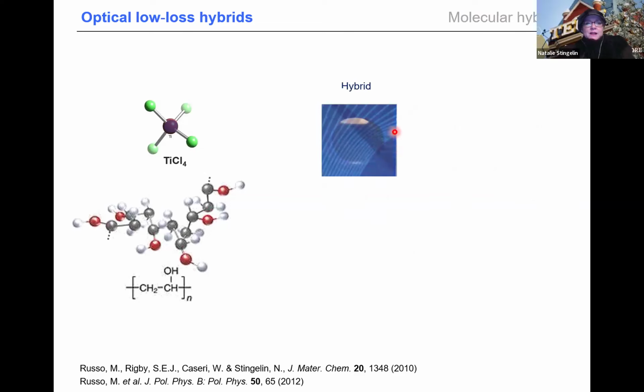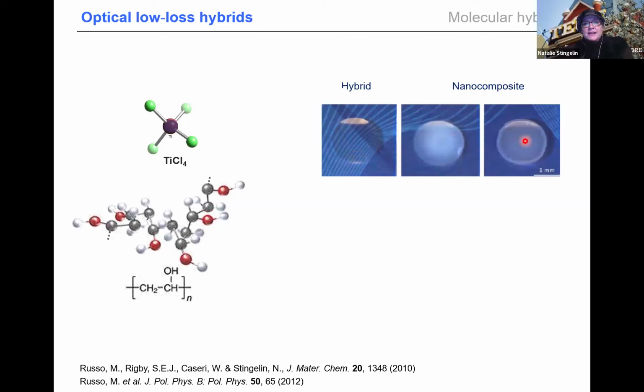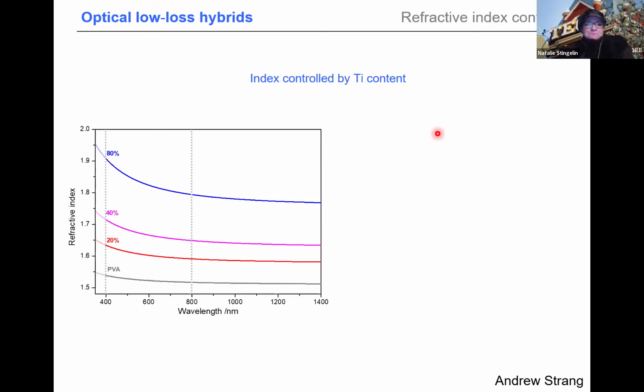So when you create this hybrid, you get a very nice transparent film. Because it's amorphous, you prevent crystallization of the PVA. And that's very different than if you would take titanium dioxide particles, because then you would have high refractive index particles, low refractive index polymer matrix that leads to scattering, as you see here. That's why we use titanium dioxide in white paint.